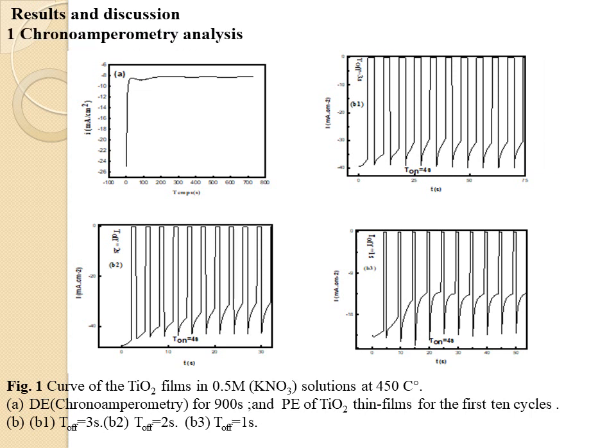The chronoamperometry curve obtained during titanium dioxide electrodeposition and pulse electrodeposition on ITO coated glass substrates is shown in Figure 1. In the conventional direct electrodeposition plating, there is only one variable parameter, namely current density. In pulse electrodeposition, there are three independent variables: time on, time off, and peak current.